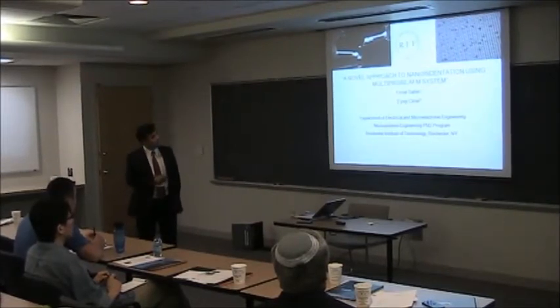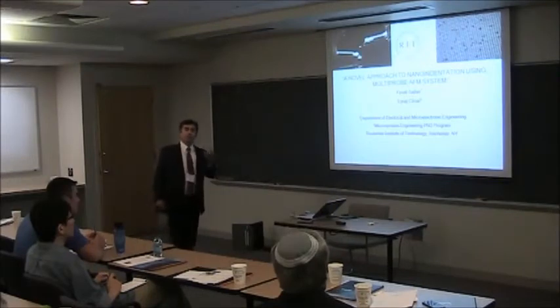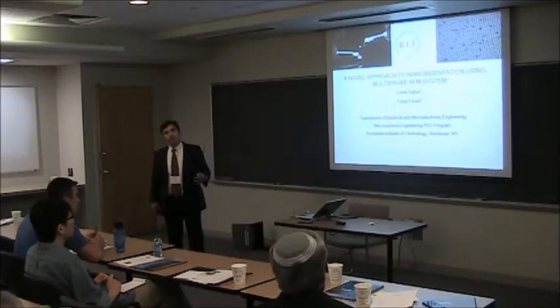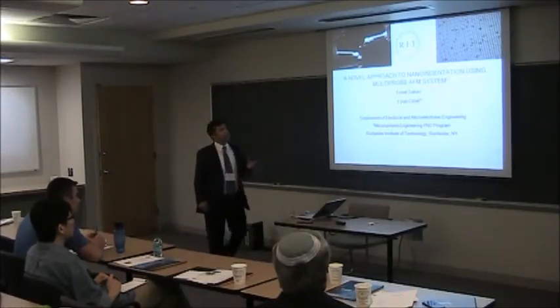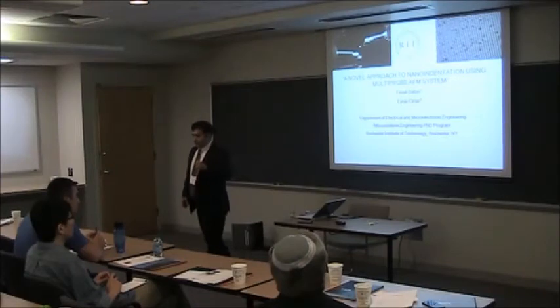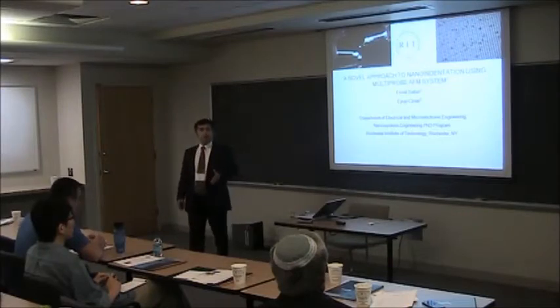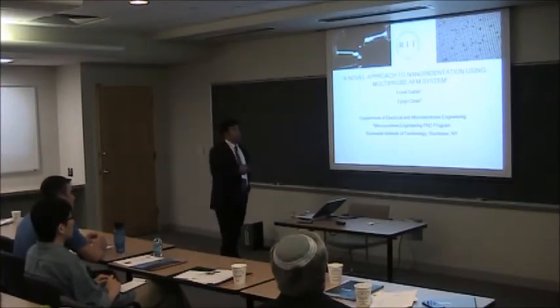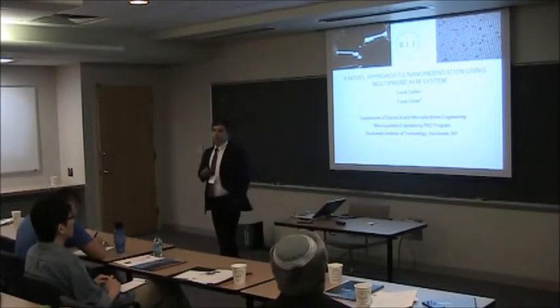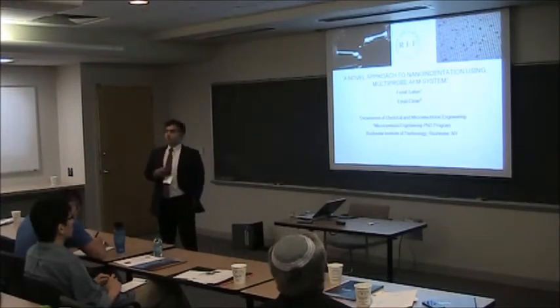What you see there is actually a bunch of cancer cells on top of PDMS pillars, which are 5 micron diameter and about 20 micron tall, so about the aspect ratio of 4. And the reason the cancer cells are up there is, when they actually are in invasive mode, it is known that their traction forces are much higher than normal cells. So our idea is to be able to measure, by looking at the dynamic change or how much they pull those pillars, the forces that those cells actually create on the surface. Thus, how invasive they are.